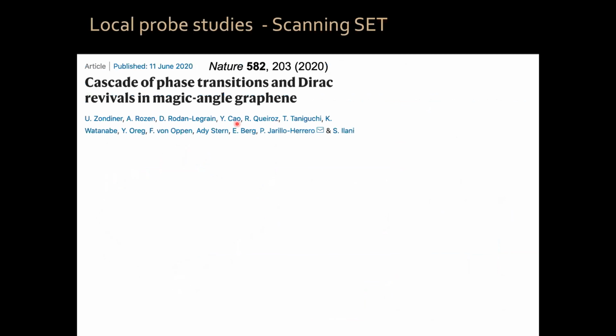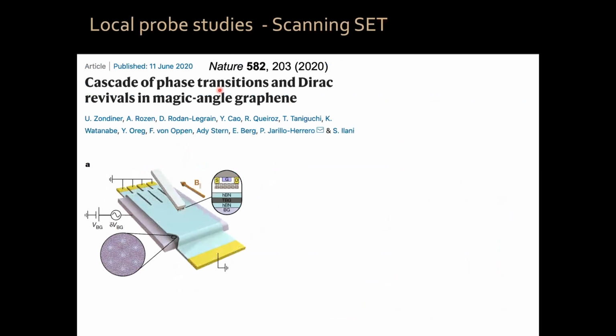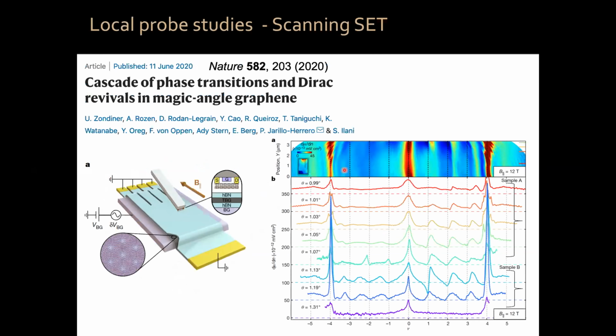With the group of Shahal Ilani, we looked at a different scanning technique. It was a scanning single electron transistor that his group has developed. Similarly, we can scan on top of our magic angle graphene devices, and we can look at different angles, and we can look at something known as the compressibility. Basically, it's telling you what the chemical potential in your system is and its variation with density. And we see that at each of these integers, at 1 electron, 2 electrons, 3 electrons per moiré unit cell, we have this sawtooth behavior indicating a cascade of phase transitions. And that is helping us a lot to understand the system.